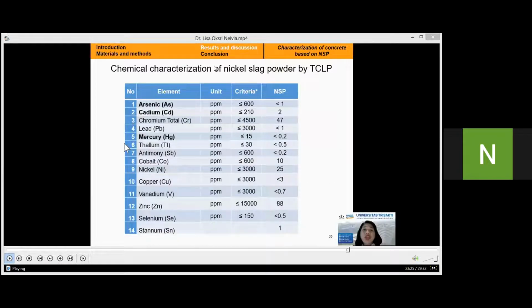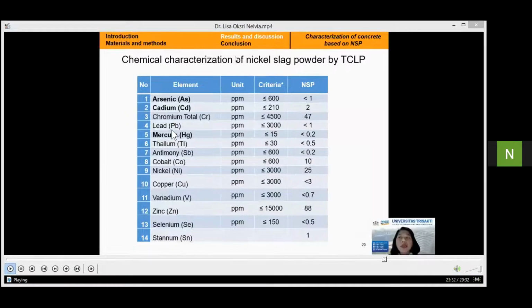According to the trace metal testing for raw material analysis, the results show that the arsenic, cadmium, and mercury levels were below the threshold for the nickel slag powder, referring to the literature. Hence, this substance is very safe for the environment and can be implemented as the new substitute of cement. This material has been accepted by the cement industry under their criteria for the trace element solid waste.